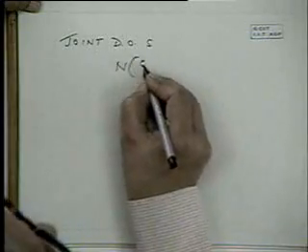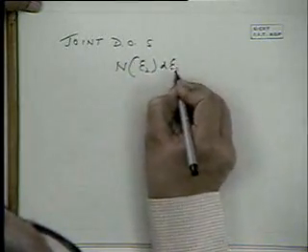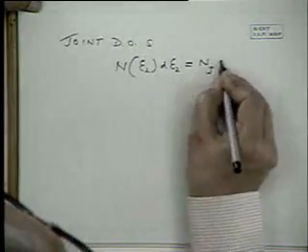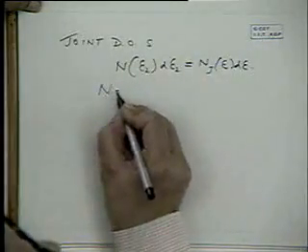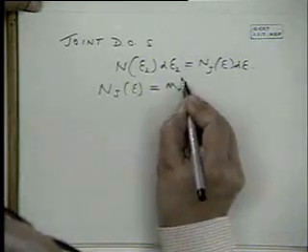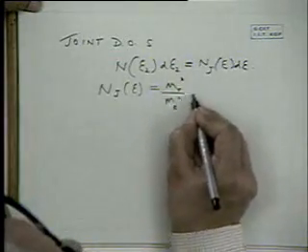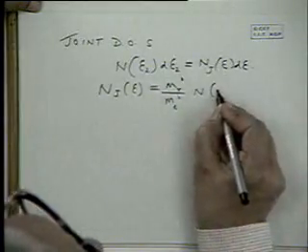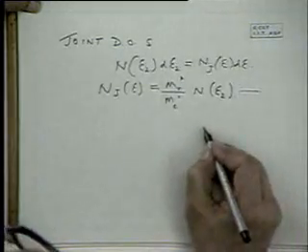So we can define a joint density of states by the relation Ne2 dE2 is equal to Nj(E) dE, and therefore Nj(E), the joint density of states, is mr star over me star times Ne2. So that is one relation we'll come back to.